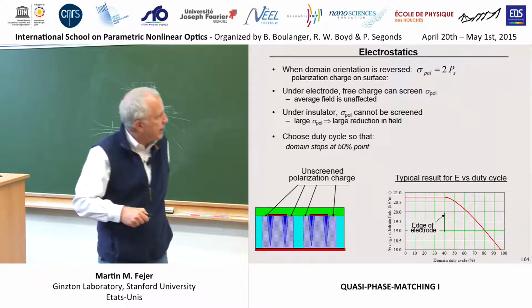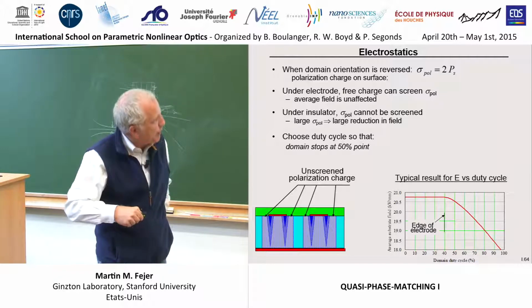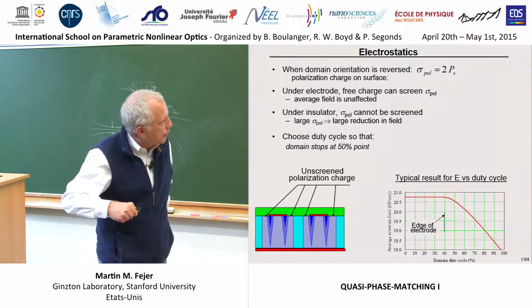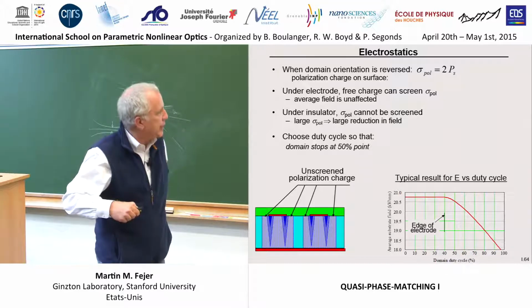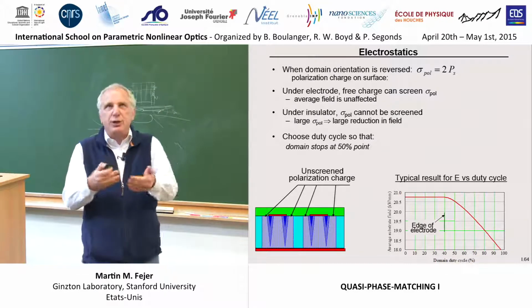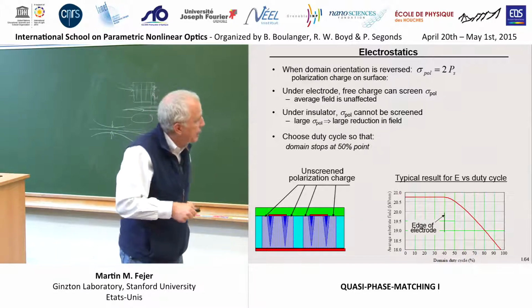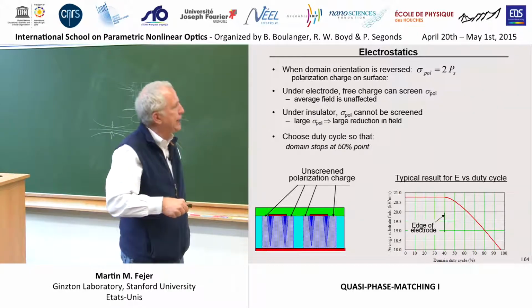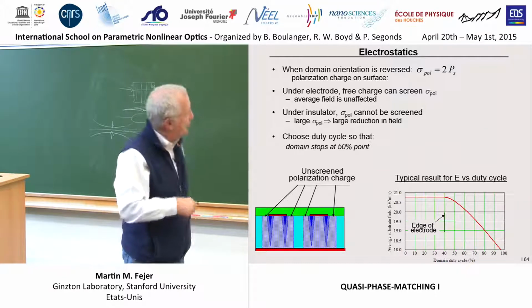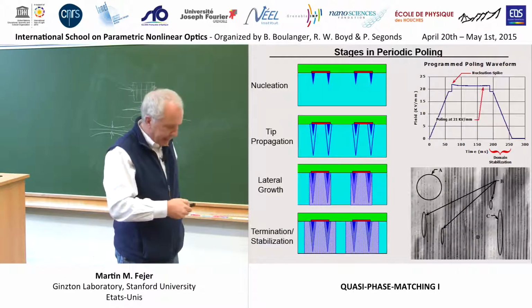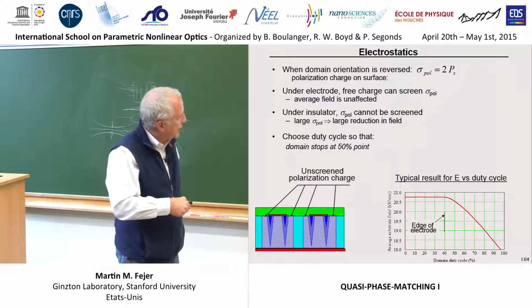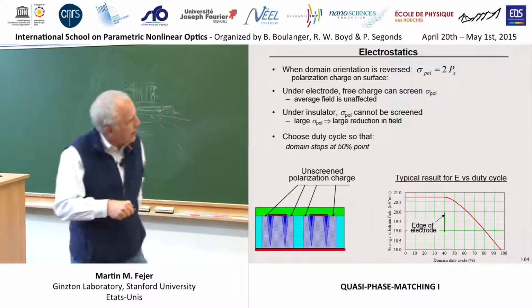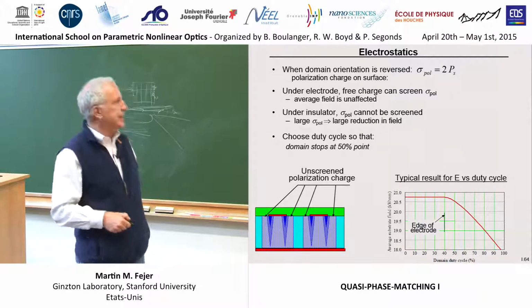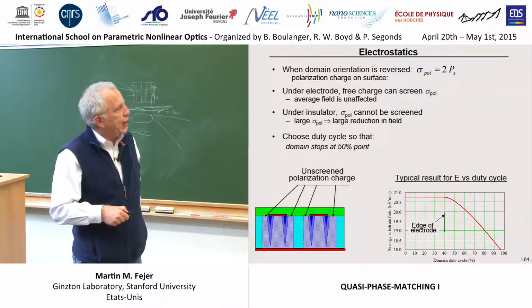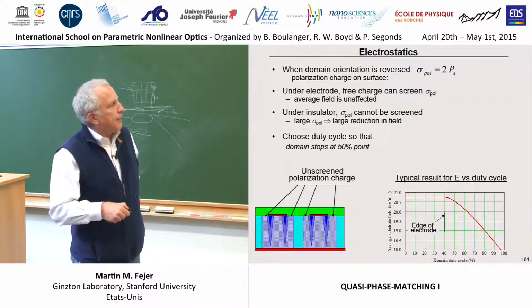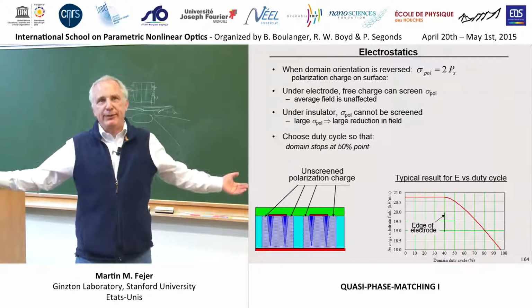And so what that does is it reduces the average field through the thickness once the domains grow past the edge of the electrode. This is an example of a calculation for a particular case. As the domain grows from the center of the electrode to the edge, the field stays constant because you're neutralizing the polarization charge with free charge on your electrode till you get to the edge of the electrode. Once the domain starts to move past the edge, the average field through the thickness is decreased by that charge forming due to the flipped domains. And you see here the charge is dropping off. And if you remember, we said that a few percent change in the field makes a 5 order of magnitude change in the velocity of the domains.